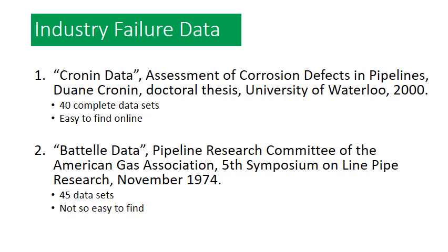For all of these data points, I have the diameter, the wall thickness, the yield strength of the pipe, the length and depth of the corrosion flaw, and the real-life hydrotest failure pressure. So what I can do is use that modified B31G equation to come up with a prediction as to what the failure pressure of that pipe is going to be, and then compare it to the actual true failure pressure. So that's what I'm going to do with a simple validation exercise.